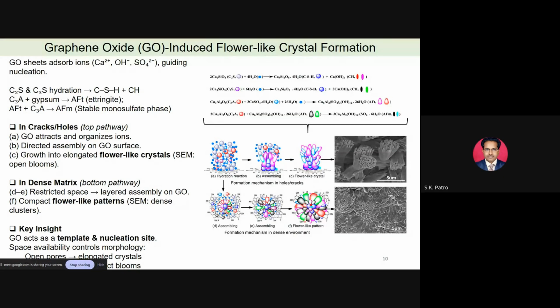So these flower-like crystals, if you look at A, B, C, D, E in the flow, you can see that GO attracts and organizes the ions in picture 1. It organizes all the ions. Then in picture 2, directed assembly on the GO surface, it assembles. Then in picture C, you see the growth into elongated flower-like crystals. And in pictures D, E, F, you see the formation mechanism in a dense environment. Finally, whatever arrangements they make themselves, they arrange in such a way that it develops a dense cluster. This dense cluster has a huge impact in modifying the morphology. When it modifies the morphology, it fills the open pores. When it fills the open pores, automatically it helps in enhancing the strength and other behavioral patterns.